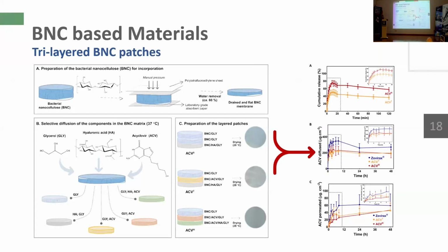How do we achieve these materials? First, we prepare bacterial cellulose membranes with different compositions, and then we assemble them in different morphologies in order to, for example, divide the amount of drug into the different layers, and also to guarantee that hyaluronic acid was always in the layer that will be in contact with the skin. And these different morphologies allowed us to adjust the release of the drug depending on this structure.